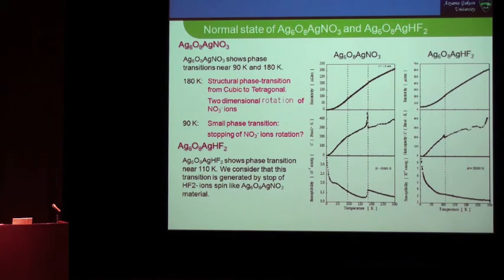This is a normal state resistivity and susceptibility data. We can clearly observe the two transitions here and here. At this transition, this is a cubic to tetragonal distortion. Inside, the NO3 is rotating two-dimensionally, and it becomes tetragonal. However, at the lowest temperature, it's probably not yet concluded. Probably this rattling is stopped. So this is a two-dimensional rotation, and at this temperature, rattling is stopped.